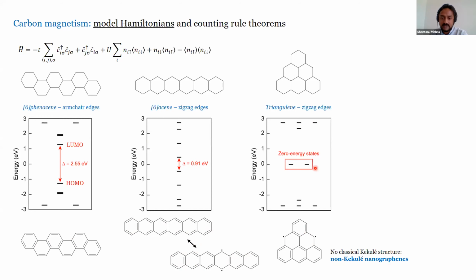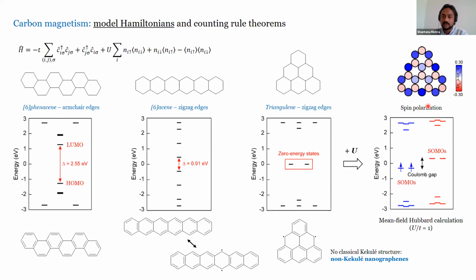Now, these zero energy states are very special because in principle, some form of symmetry breaking transition could always occur that can lower the energy of this state. And it turns out that if you apply some amount of Coulomb repulsion, then you're going to spin polarize the system. So what was essentially a zero gap system has now become a gap system. So a Coulomb gap has opened up, but you see that the spin symmetry is broken. So you have now singly occupied orbitals of only one type of spin, while the counterpart spins are unoccupied. That's shown graphically in the spin polarization plot. You see that preferentially spins of only one kind occupy the edges, while the other spin is inside of the molecule.